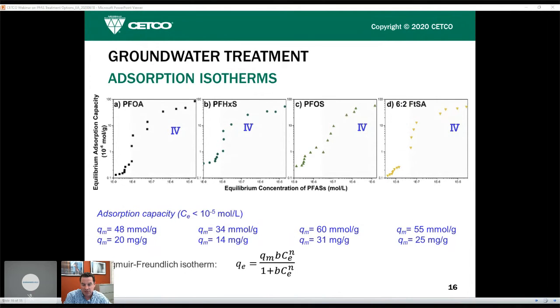But what we found is the full absorption capacity can range somewhere between 14 to 31 milligrams per gram. If you compare that to other media like GAC, the absorption capacity is a lot less. It's less than 1 milligram per gram. And also the absorption capacity is dependent on the molecular weight. So depending on the PFAS composition, you might see slightly different absorption capacities in total.